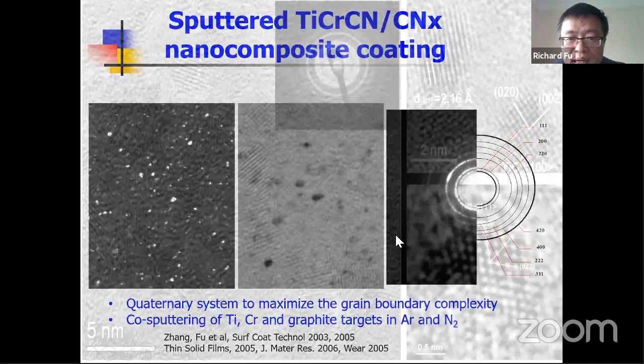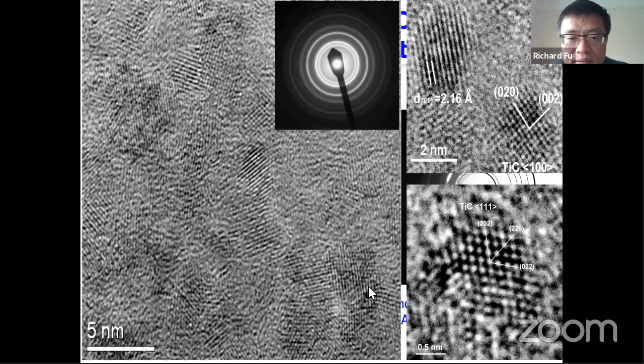We can further use a high-magnification transmission electron microscope to observe the coating and optimize it. We can see that there are truly a lot of nano-sized particles with different orientations. Between the different nanocrystals there are amorphous regions, which form the matrix. Through the lattice, we can also know that there are different carbides or nitrides for the different orientations. So this achieved very good performance.